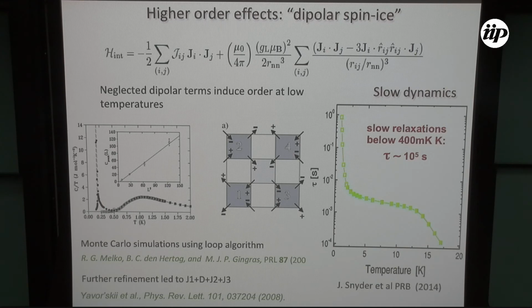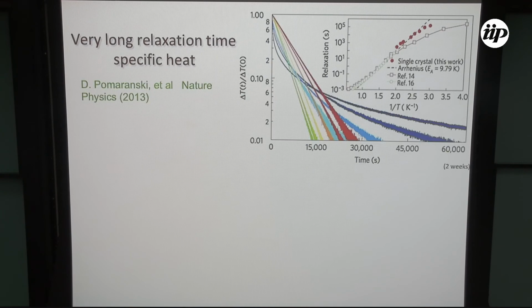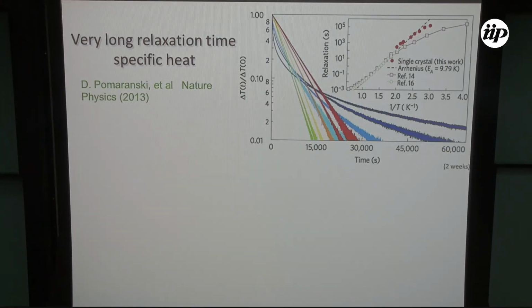So one explanation was that there's this really huge increase in the characteristic relaxation time of the system. See, this is temperature, and this is in seconds, the system goes from 10 to the minus 4. When you're close to 1K, the system has already a relaxation time of the order of 1 second. And if you check this slope, it's going to be really, really steep. So in principle, you should wait for a really long time to be able to see any equilibrium phenomena in this system.